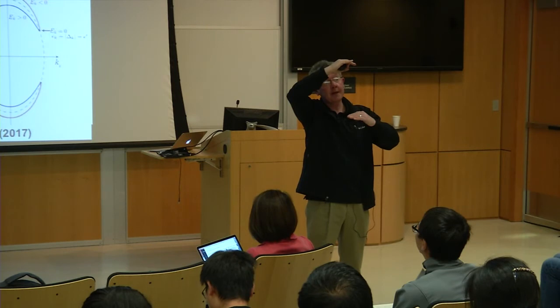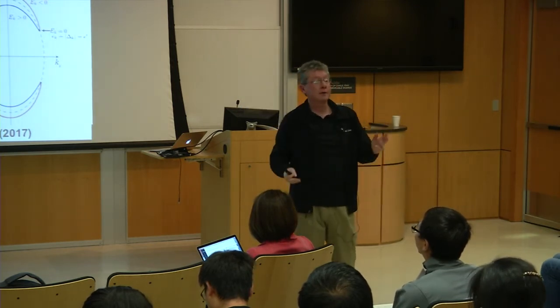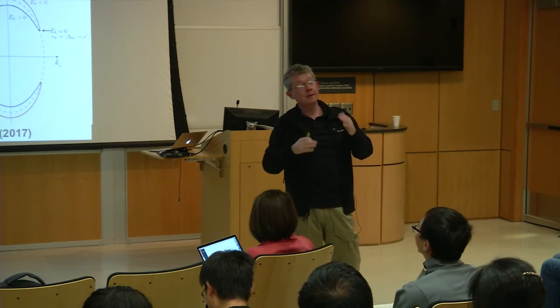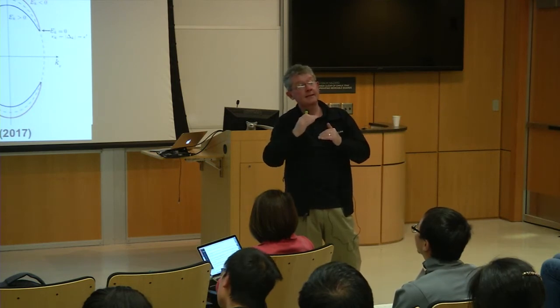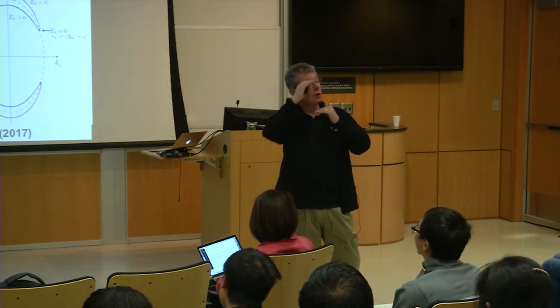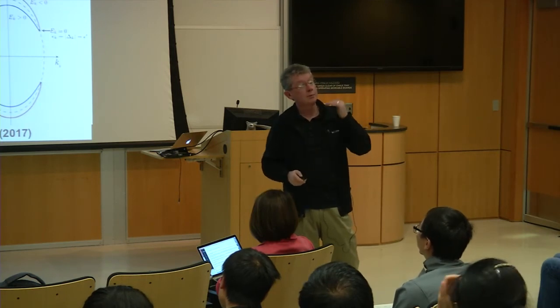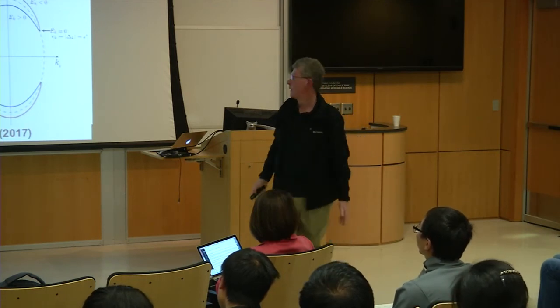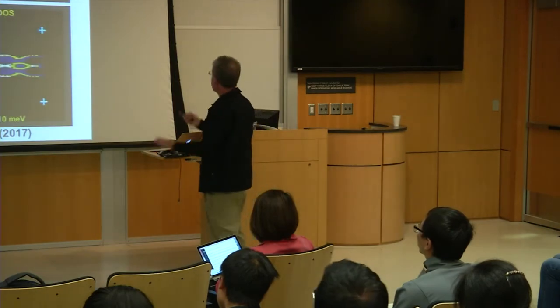So we're thinking of 3 active orbitals, 2 of them being degenerate. However, this compound is orthorhombic, and the orthorhombicity lifts the degeneracy between dzx and dyz. So all 3 primary orbitals should be split from each other in energy. Okay, so now we carried out these experiments.